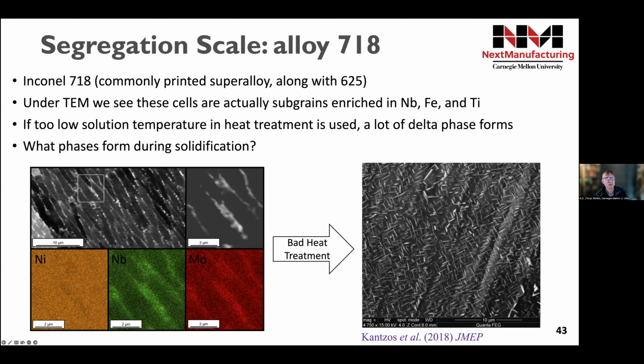And the interesting point about this is when you print it and you apply some standard heat treatment, the microstructure that you get not only is organized with this very fine columnar solidification microstructure, but even a slight amount of heat treatment gives you this crisscross pattern. What you're seeing are particles, actually platelets, of the delta phase. Delta phase is known, but you don't normally get this much of it, and it's not particularly good for properties. And so you ask, well, why is that happening? It's basically because of microsegregation. So that's a 2-micron scale bar.